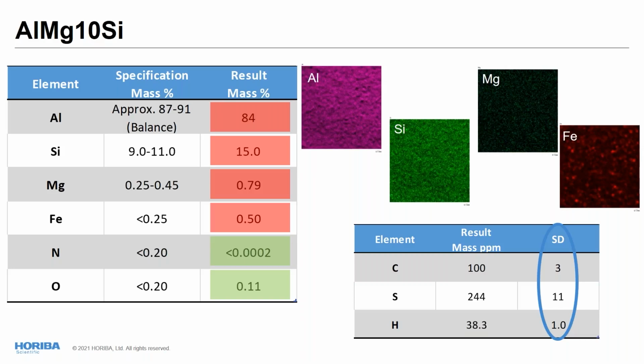Even if not specified, we perform analysis for carbon, sulfur, and hydrogen, and they were all in the high ppm value. And you can see also the interesting thing that even at high ppm value, we had very interesting standard deviation with about only 1 ppm standard deviation for about 38 ppm hydrogen. That is very, very stable, providing very high accuracy even on this type of values.